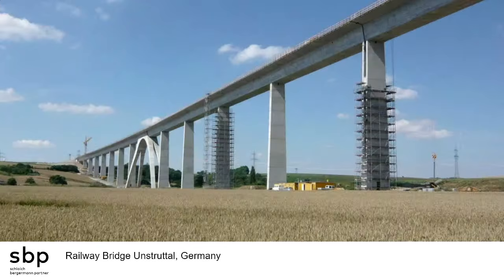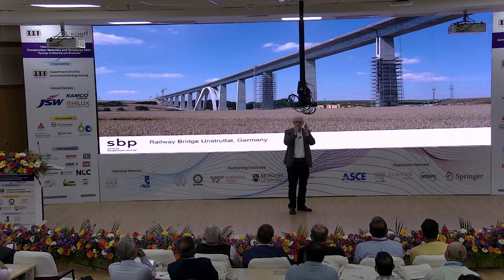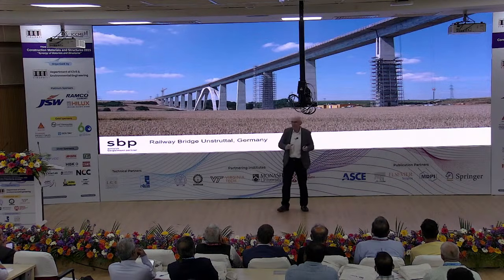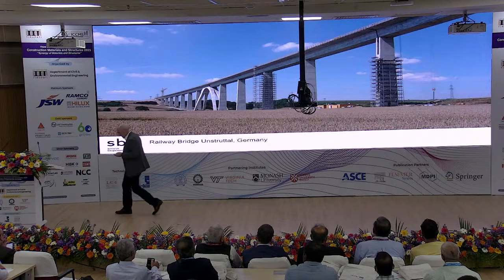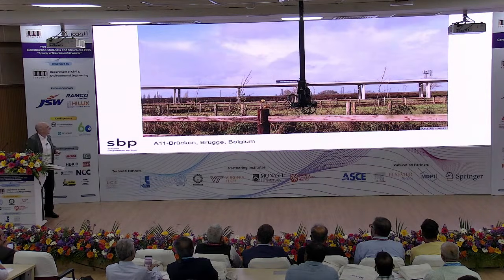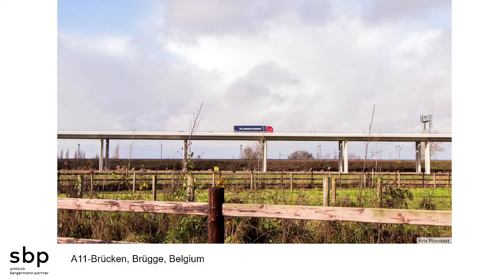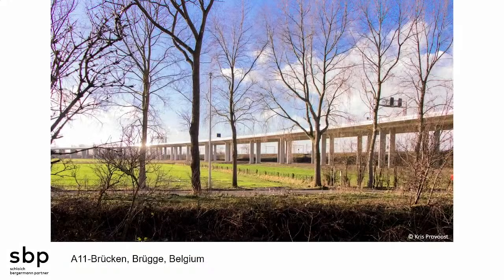So this is the bridge, and you see even at the joint, there are no bearings, because there are two walls on the mast, on the pier, and these walls are monolithically connected to the deck. We applied the same system to highway bridges, and you can see that it's a very humble highway bridge, but still small spans, only 1.20 meters height, and very slender piers of high strength concrete that can take care of all the movement. So this is a 600 to 700 meter integral bridge without any bearings, any joints, and they are very cost efficient, because there are no expensive bearings and no expensive joints.